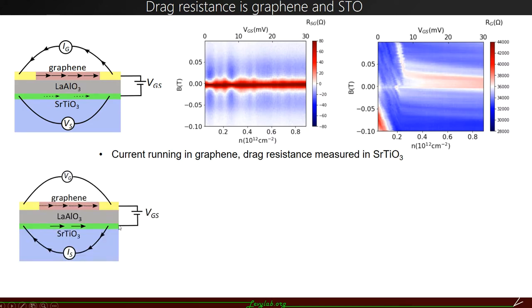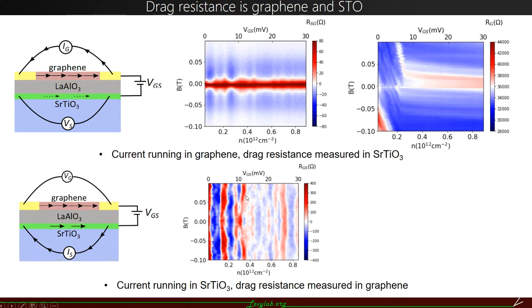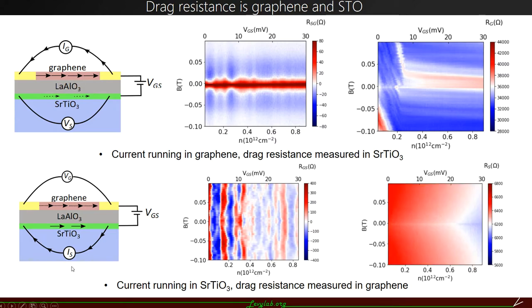Then we run the current in SrTiO and measure the drag voltage in graphene. We can see these stripe-like features as we change the carrier density in graphene. And this is the voltage we measured. This is the SrTiO voltage measured at the same time. So if we correspond these four figures together, we can see the drag signal in SrTiO is greatly enhanced when the SrTiO is in a superconducting region, and also these stripe-like features are very similar to the resistance in graphene.